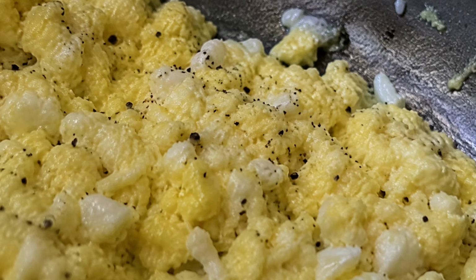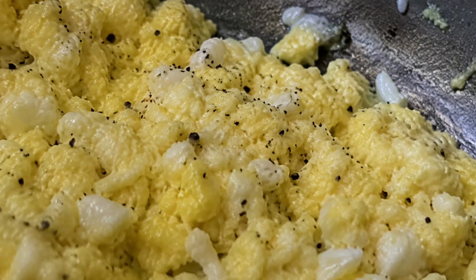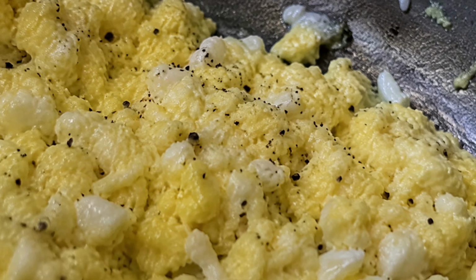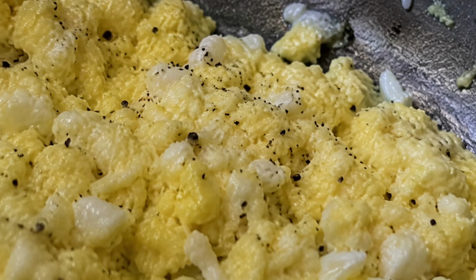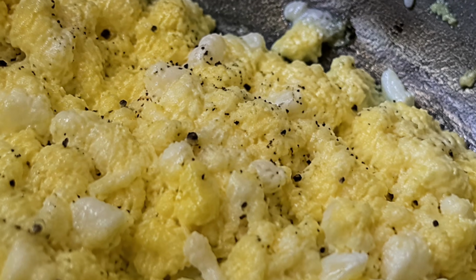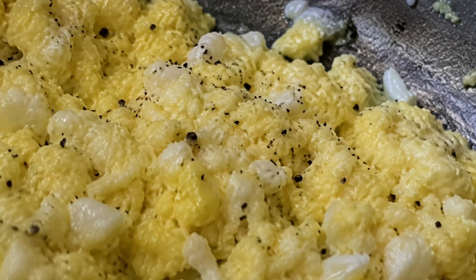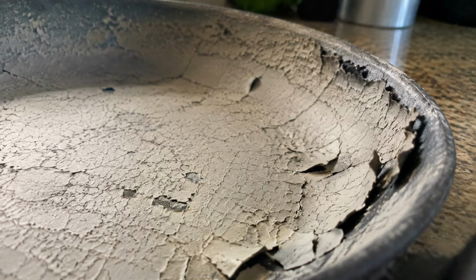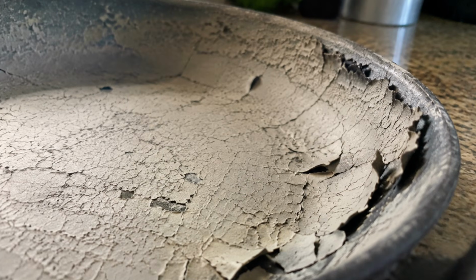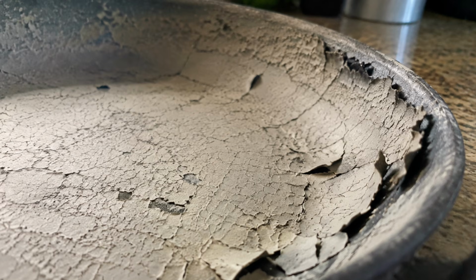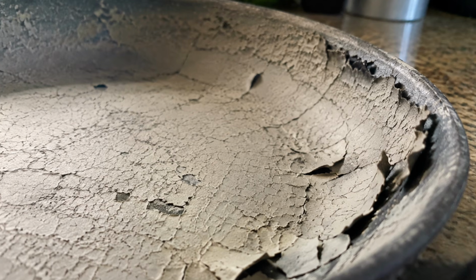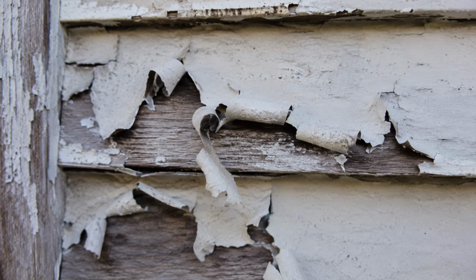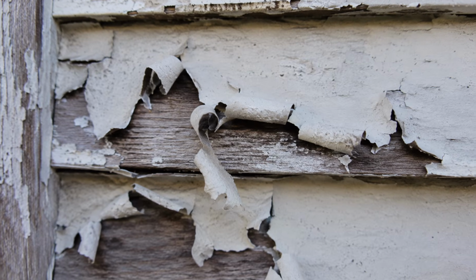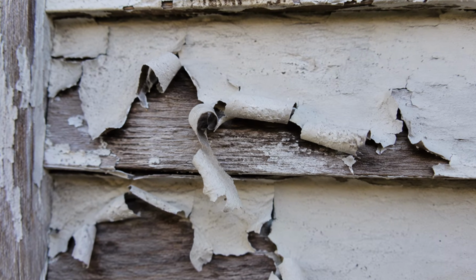Second, flaking. If your pan sheds little black flakes into the food, that is not the iron failing, and the flakes, though they are nothing you want, are just bits of overbuilt coating. It happens when seasoning was built too thick too fast, heavy layers on heavy layers, or on top of old burnt food that was never cleaned off, and the pile finally cracks and lifts like old paint. The fix is the honest one.